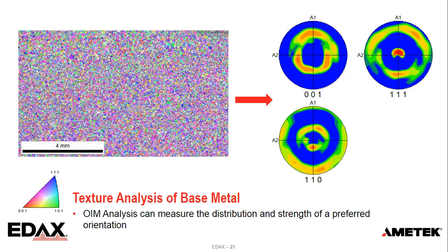The center of the pole figures shows the sample normal direction. The A1 shows the top to bottom direction, so A1 is the top of the map. A2 is the left-hand side of the map. If you use your right-hand rule, you'll see how that aligns with that map. So what this shows us, if we look at the 111 pole figure, is there's a strong peak in the center of the 111. It's a little bit offset, kind of coming out the center of the sample.